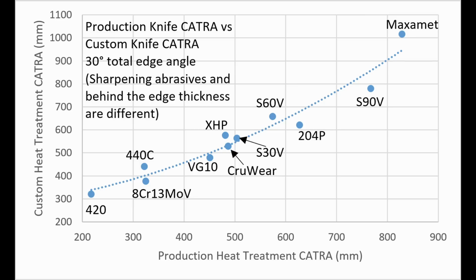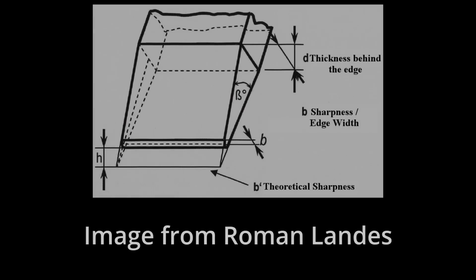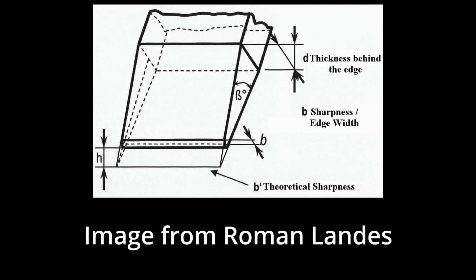However, you will notice that my results were consistently somewhat higher than the knife manufacturer, averaging about 17% better. This is not because my heat treating was superior. Rather, it's due to differences in the design of the blades, the edge geometry, and how the blades were sharpened. The behind-the-edge thickness was greater with the production-made test knives. Also, the knives that I tested were sharpened with an Edge Pro, which keeps the edges very triangular, without rounding.